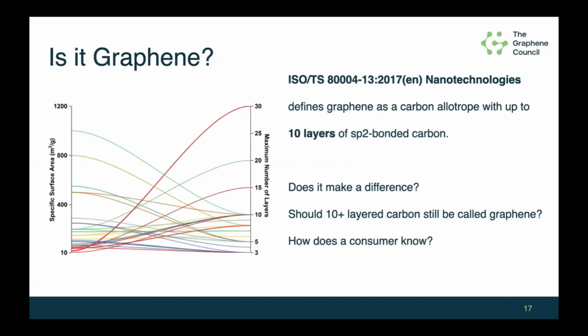Next is, as Terence said, the ISO standard defines graphene as a carbon allotrope with up to 10 layers of sp2 bonded carbon. This chart here shows the data reported from graphene based TDSs, and we see that some of them report the maximum number of layers, even up to 15, 20, and 30, and then it is still called graphene. So at this point, it makes you wonder whether 10 plus layered carbon should still be called graphene, right? And how does the consumer know whether this is graphene, it is not graphene, or is it just graphene nanoplatelets or just bulk graphite?